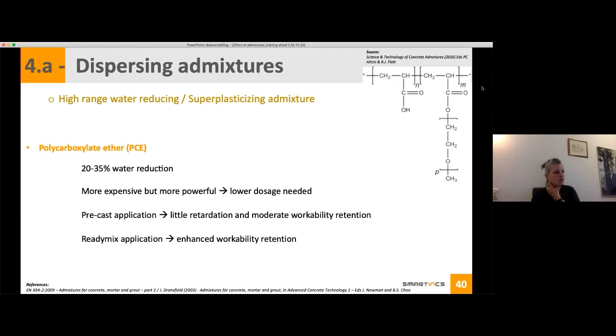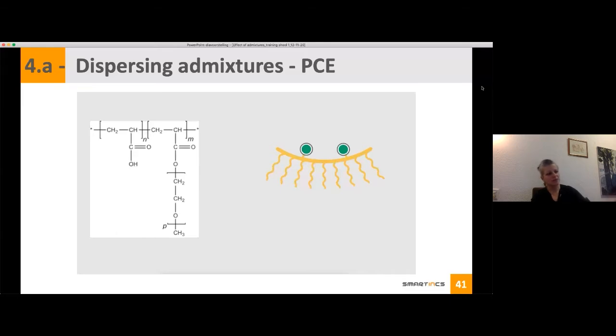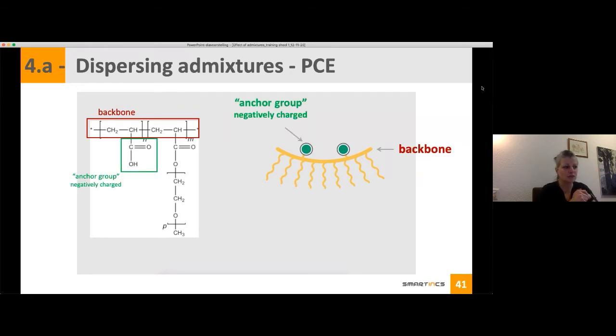And I want to say a little bit more about PCEs. So this is a chemical formula on the left of a PCE, but often maybe you will see also in literature, they are schematically represented as what you can see on the right of the screen. The first part is called the backbone. And then you have the carboxylate groups that are called the anchor groups. They are negatively charged. And then you have the side chains. So what is really nice about PCE, you have 3 different components. In terms of chemistry, you can act on every part of the PCE, which means the properties you can target for the PCE are really a lot.